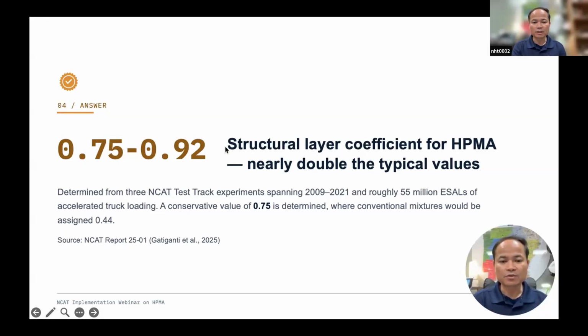And the number that I've shown here is that for the layer coefficient we typically use 0.44 in the 1993 pavement design guide, or in the case of the Alabama DOT, they use 0.54 for the structural layer of the conventional asphalt mixture. Now, when we did all the analysis, and this is published in the NCAT report 25-01 that Nathan mentioned earlier, we found that the layer coefficient for HPMA can be as high as 0.92, and the lowest number that we found would be 0.75.